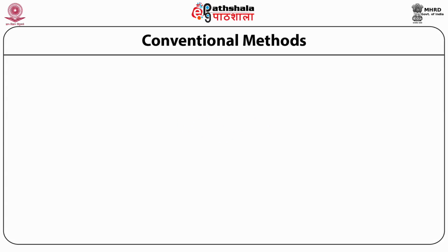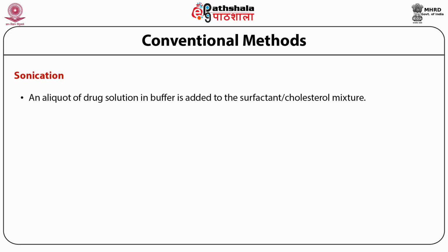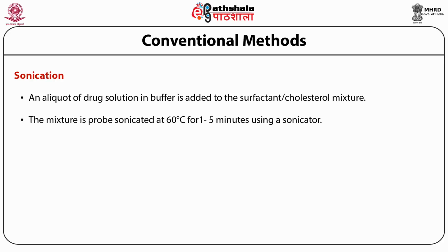Conventional methods. Sonication. Here, an aliquot of drug solution in buffer is added to the surfactant-cholesterol mixture. The mixture is probe sonicated at 60 degrees centigrade for 1 to 5 minutes using a sonicator. The longer sonication leads to smaller particle size.